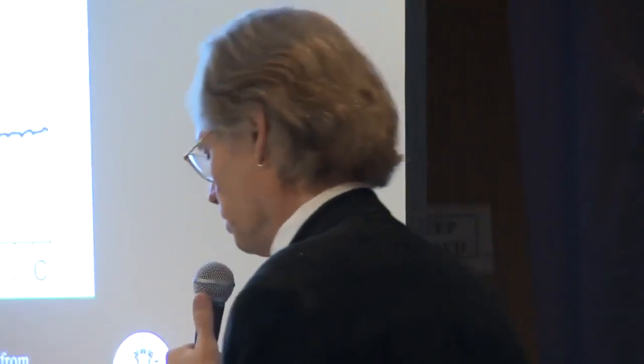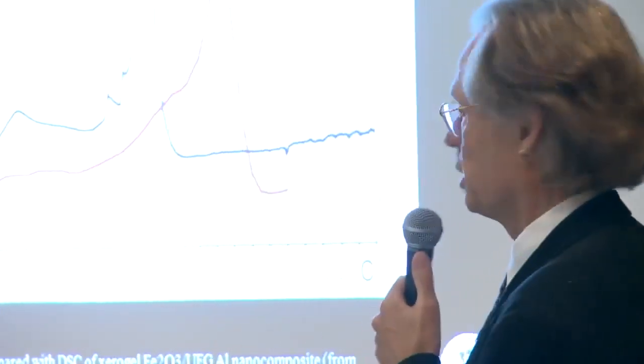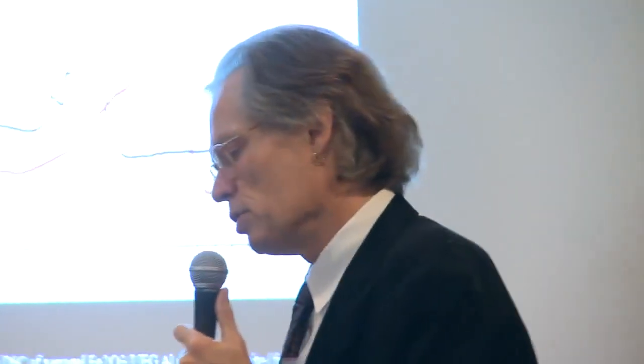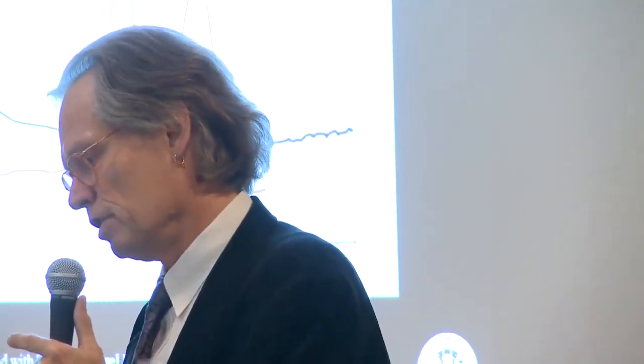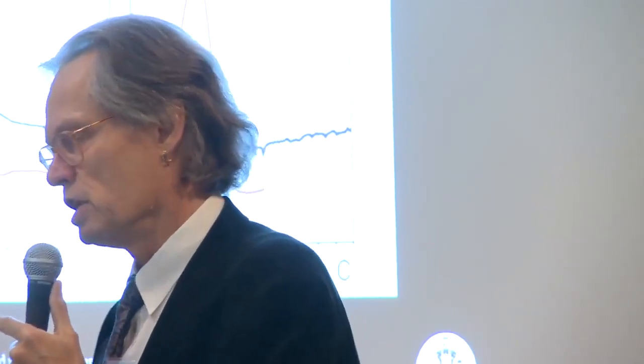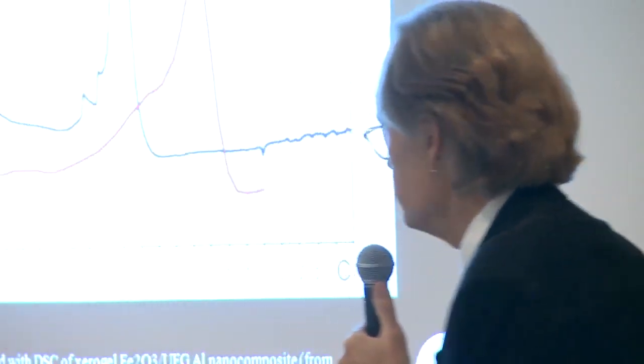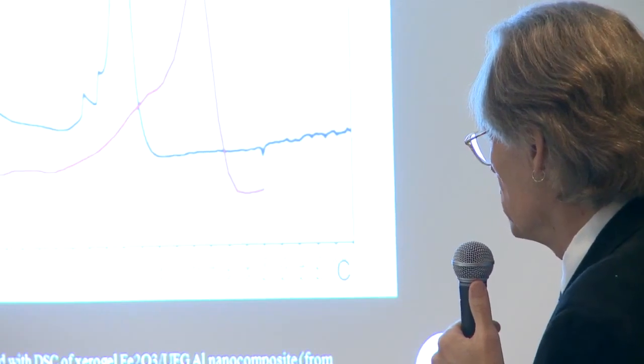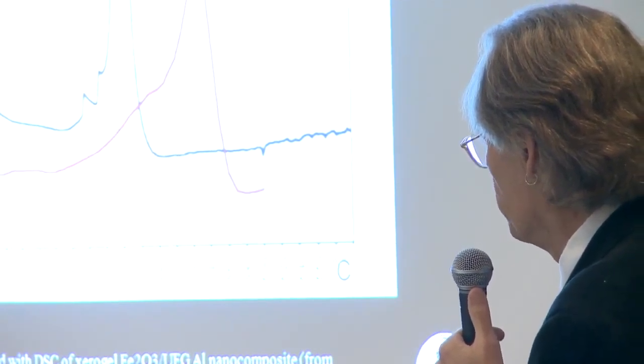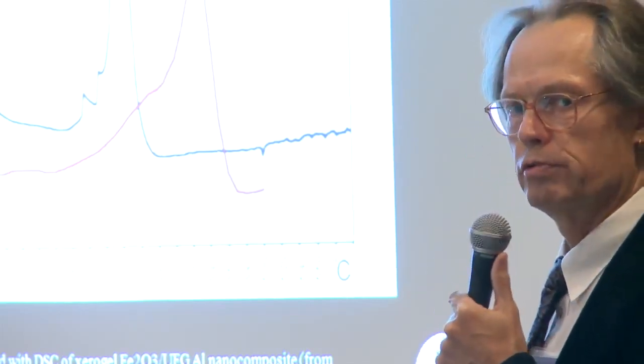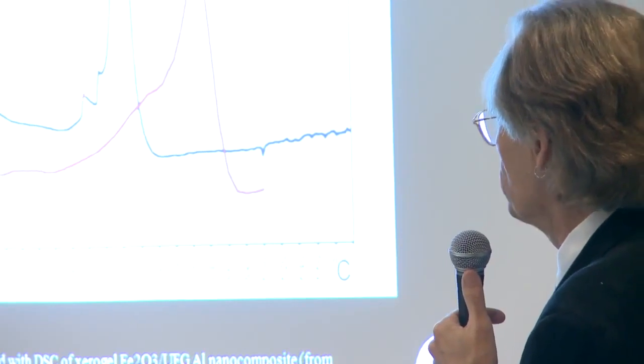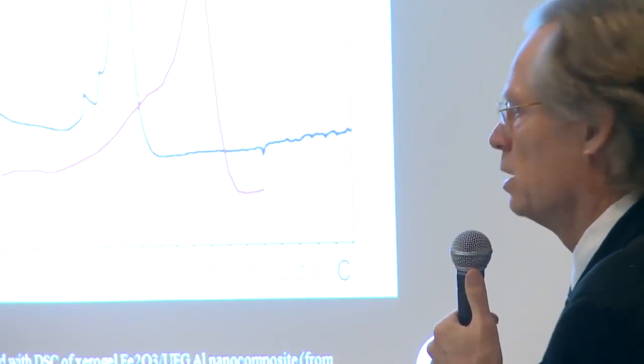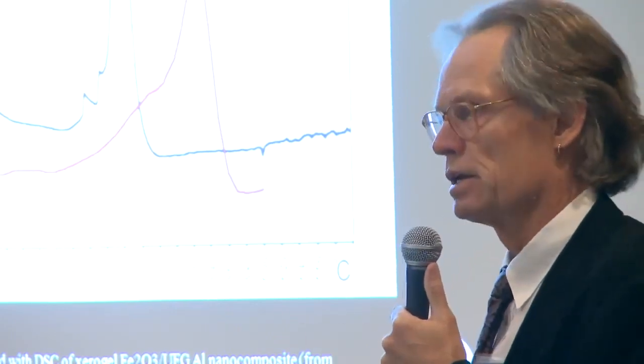But applying a microtorch is a nice demonstration. It's not real scientific. But if you want to have a quantitative measure of the heat developed in this reaction, you put it into an instrument called a differential scanning calorimeter, which is a device where you heat up the item, the little chip, and you measure the flux of heat going in and out of the sample. And here, this is the blue line. So we are heating it up in degrees Celsius, and suddenly here at around 430 degrees, it goes boom. It goes simply off the roof, and the needle bends, and you have a very sharp, very narrow spike, energy being released, indicating a chemical reaction.